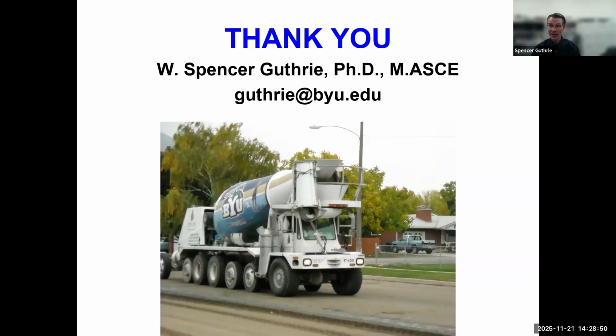It has a lower tensile strength than compressive strength. And there are pavement design techniques to ensure that the thickness of the cement treated base layer is such that we do not have fatigue cracking of the actual cement treated base layer under the asphalt. And that would again be the subject of another presentation, right? We cover that in my pavement design class. So it's an important recognition. Stiffer layers need to have fatigue cracking as a consideration, a criterion in the design process. Thank you.